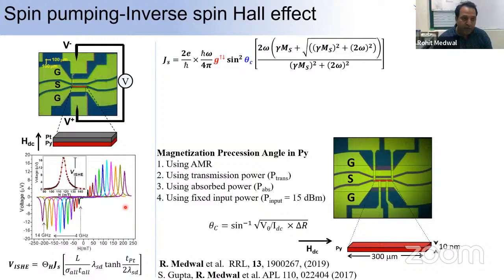I would like to highlight that the spin current pumped from the ferromagnetic material to the platinum mainly depends on two factors: the spin mixing conductance, G mixing, and theta c, the precession cone angle I just explained. When pumping the spin current there are two contributions. One is whether the interface between the ferromagnetic material and the platinum is very clean, which is defined by the spin mixing conductance. The other is the precession cone angle of the ferromagnetic material, at which we apply the HRF to allow the magnetization to precess.